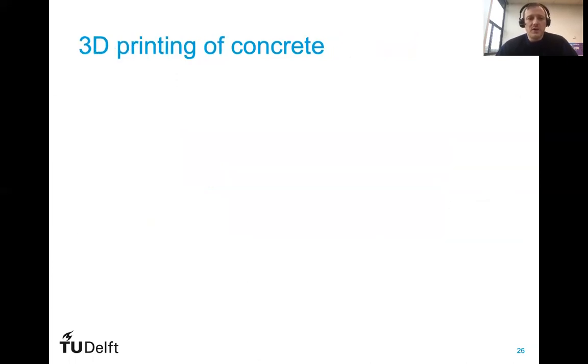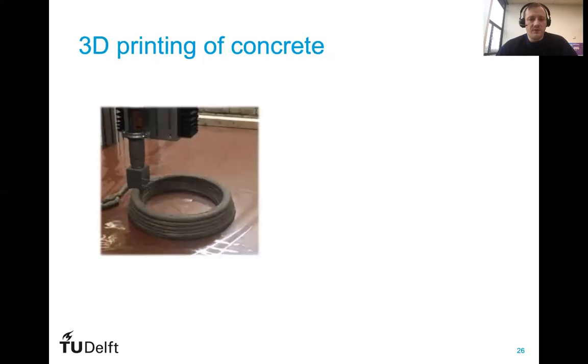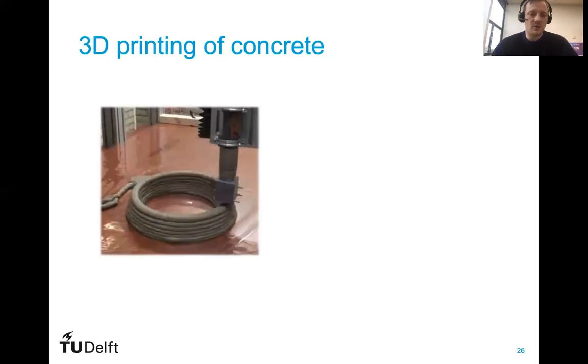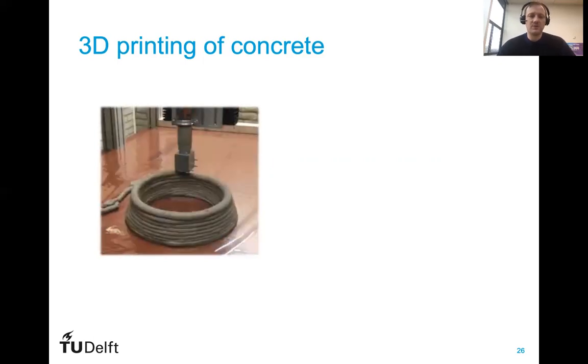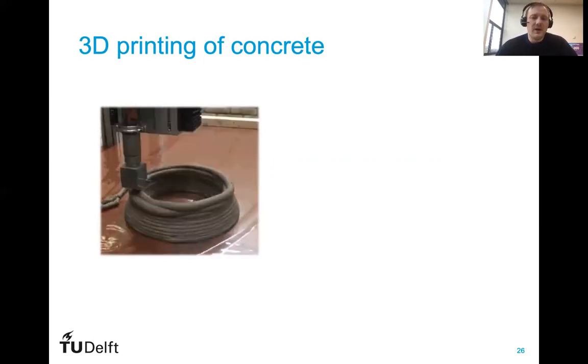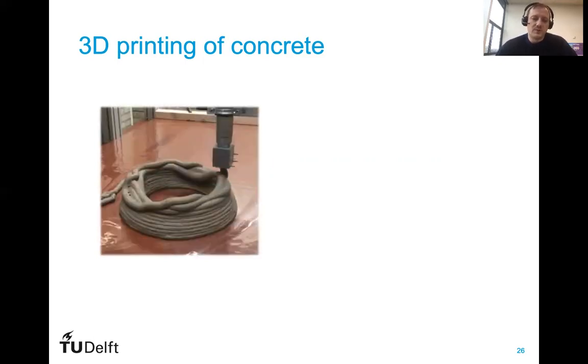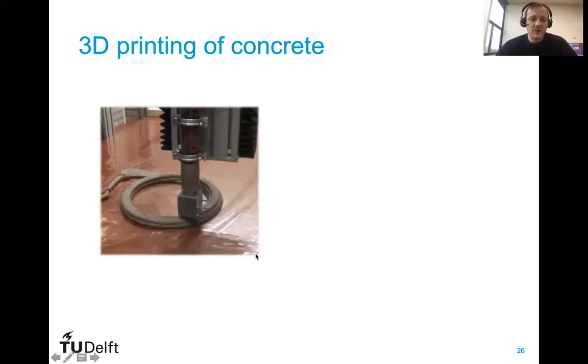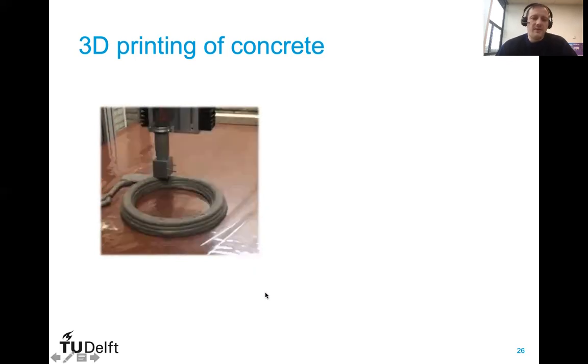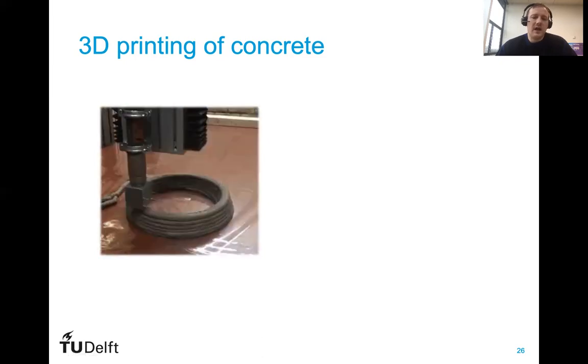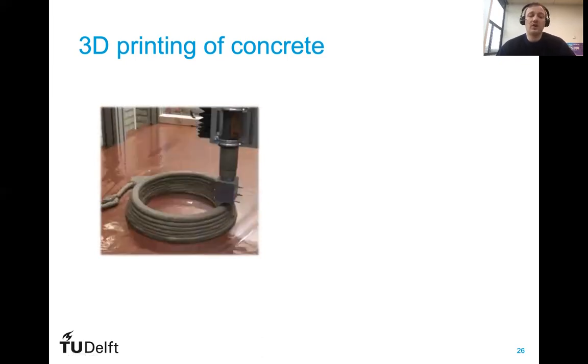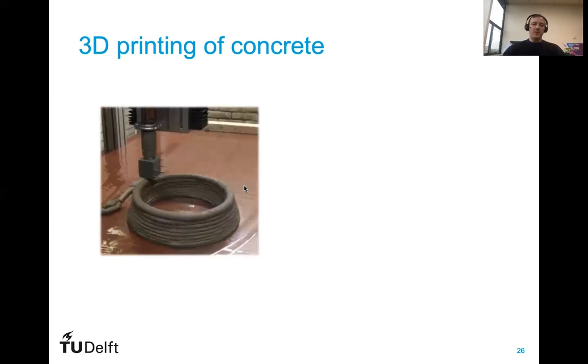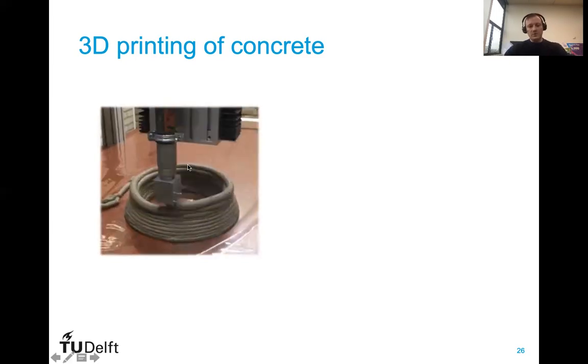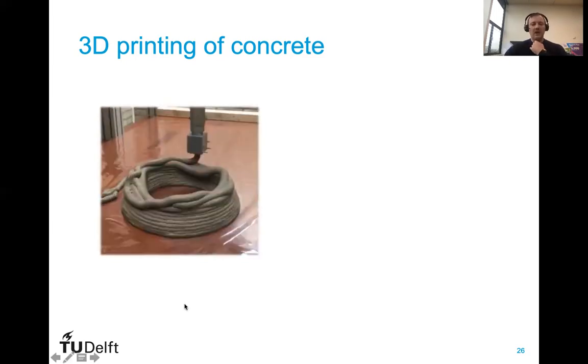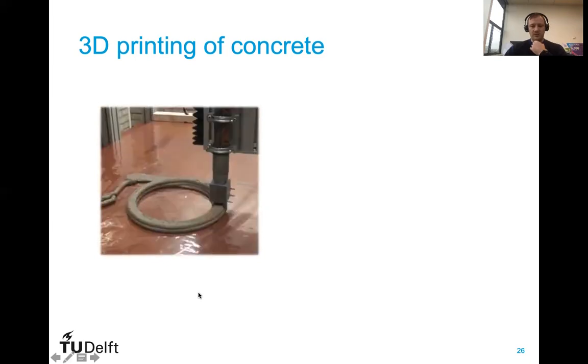We have also been working on 3D printing of concrete. Of course, a lot of people are working on that. So you have an extrusion-based process where you extrude layers of material on top of previous layers and try to build up a structure. However, as you see in this video, if the parameters are not done correctly, the structure will collapse. So what we need is to be able to predict at which point the structure will collapse in the fresh state in order to optimize the printing process.